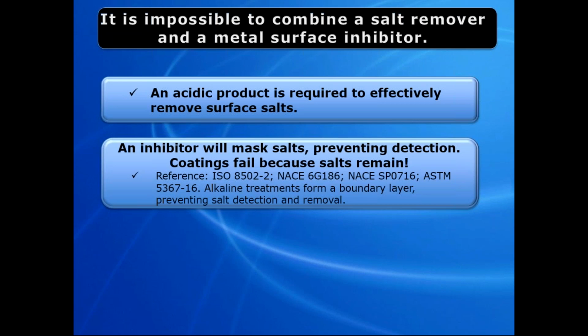Bear with me. The ISO 8502-2, in the scope section, the fourth sentence, states that amine inhibitors can form a hydroxide barrier, not water soluble, over the substrate and prevent the water from contacting the underlying salt for its removal. NACE 6G186, page 9, states that consequently soluble salt testing is usually performed prior to inhibitor application, just so you can check for those salts accurately.